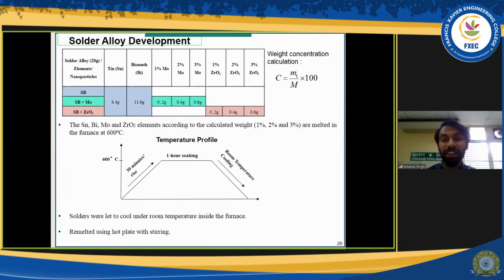But choosing SnBi gives me another problem, which is the mechanical properties. The mechanical properties of SnBi are not up to the level of SnPb, simply because of the low melting temperature. With low melting temperature, the diffusion process is not as active as in a high melting point solder alloy, so the intermetallic layer is not that strong. That is why I try to add in molybdenum and zirconia. Why? Molybdenum is a transition metal and zirconia is an oxide. I want to see the effect of nanoparticles of different phases by themselves. This is what other researchers have done also. They used two different types, and we see what happens.